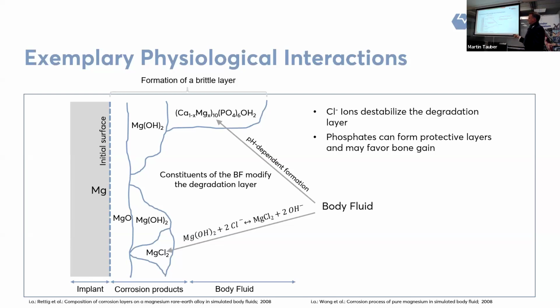On the other hand, there is a very complex compound that forms on top of the implant. It's an apatite, which appears due to the shift of the pH. With higher pH levels, the solubility of these apatites drops, and they recrystallize on top of the implant structure. This is kind of a counter reaction to the one we were just describing, because in this case another layer forms on top of the implant, which will slow down the degradation. But this one has another positive impact, because this is basically the nutrient for osteoblast cells, the cells that build up bone. So what we can expect is that in the vicinity of these magnesium implants, bone growth will be boosted by this partial reaction.